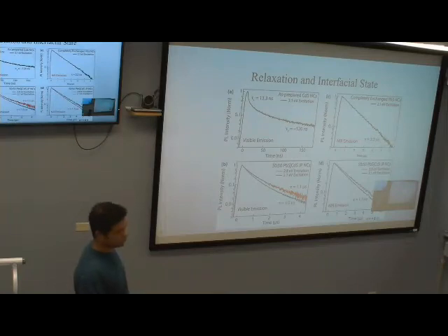So that's why they're saying that whichever range you're exciting, it is not relaxing from the cadmium side. But it matched pretty closely with the lead sulfide, which is 2.2 microseconds, this is 1.7 microseconds, and this one is in the IR emission part.